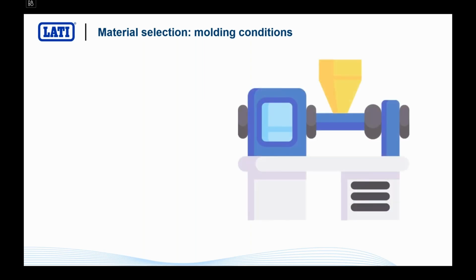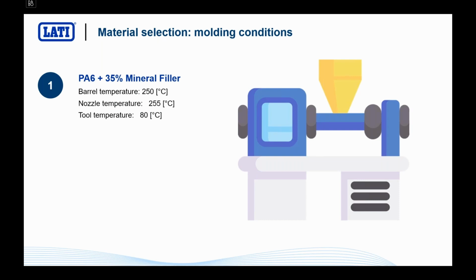Let's see the molding conditions that we have set up on our injection machine for our design of experiment. For the polyamide 6 35% mineral filler, we have selected 250 degrees C for the barrel temperature, 255 for the nozzle, and 80 degrees C for the tool temperature. Very typical injection molding condition. We will keep the same molding condition for all of the materials that we are going to test this afternoon.